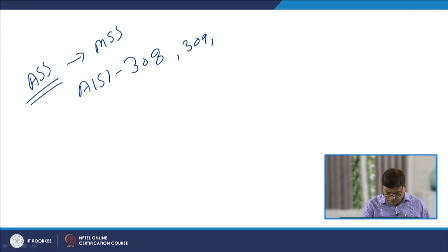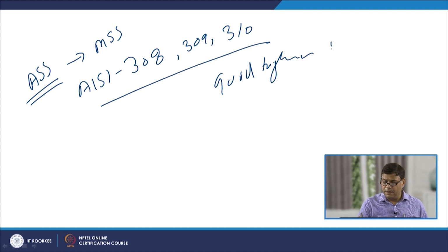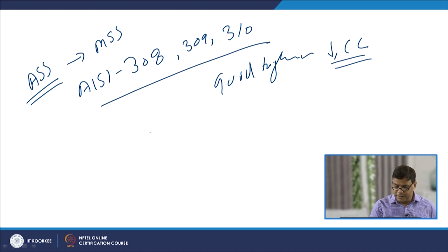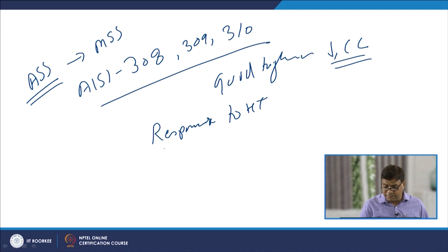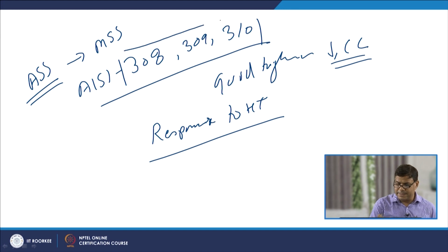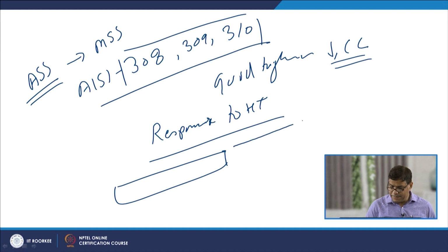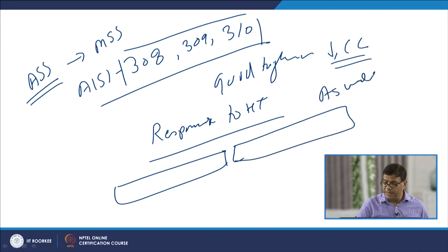There are a few grades of austenitic stainless steels which are effectively used for the welding of martensitic stainless steels, and these grades are like 308, 309, 310, and all of these offer very good toughness and reduce the cold cracking tendency of the weld joint. But before choosing a particular grade, we must assess the response of the weld joint to heat treatment. These are mostly used since the austenitic stainless steel fillers do not respond to heat treatment. So, these are normally preferred when the MSS weld joint is to be used in the as welded condition.